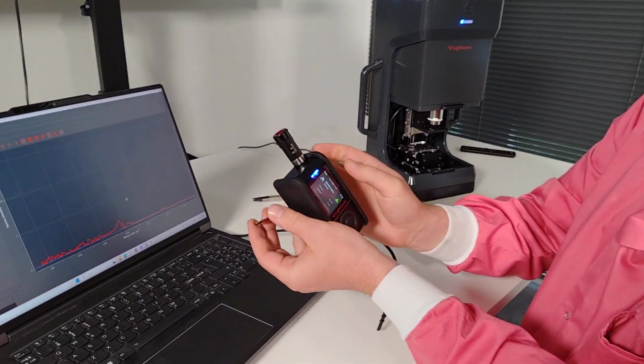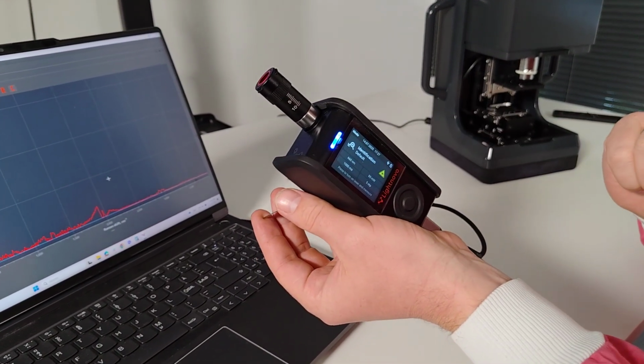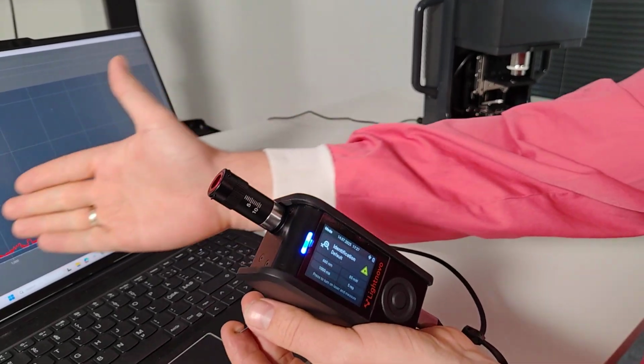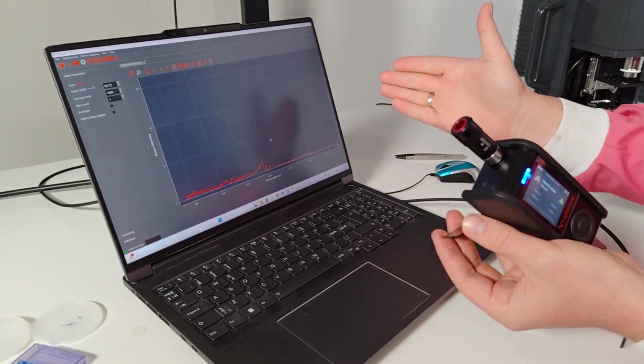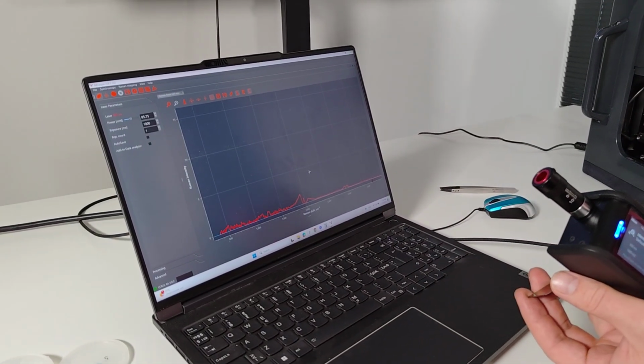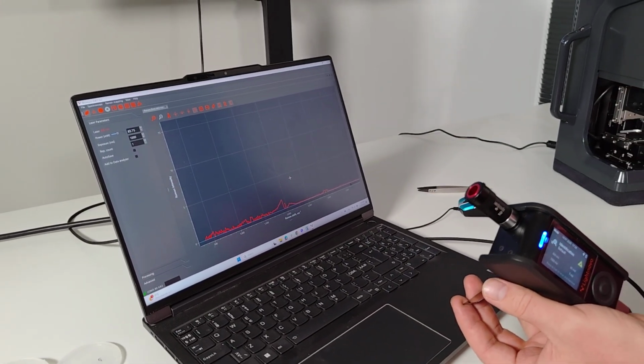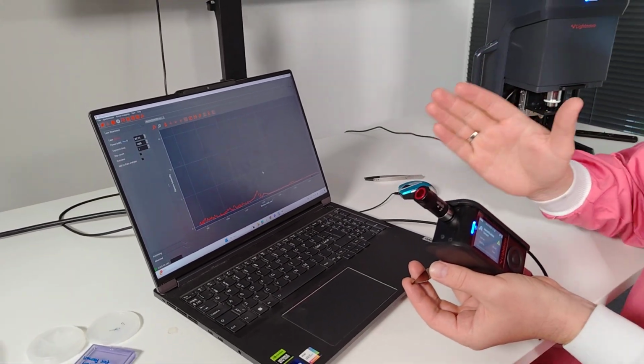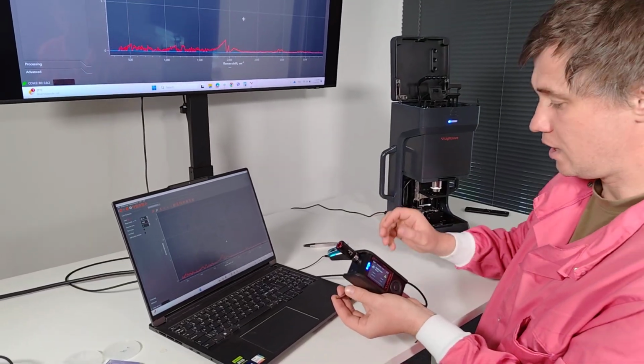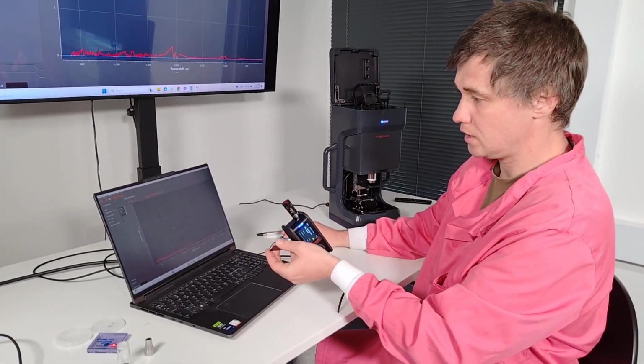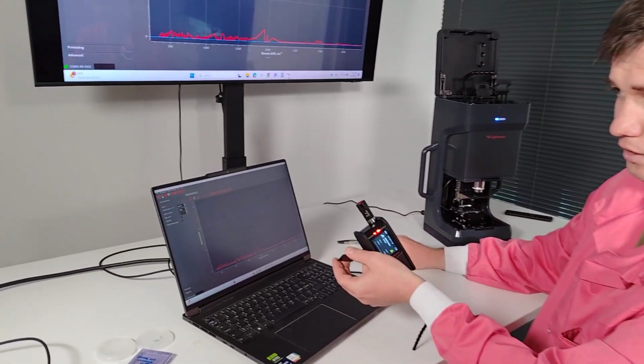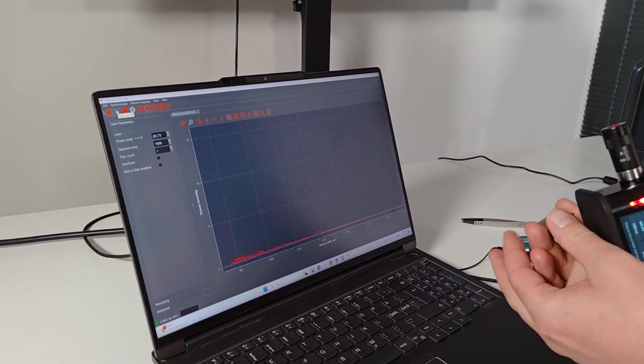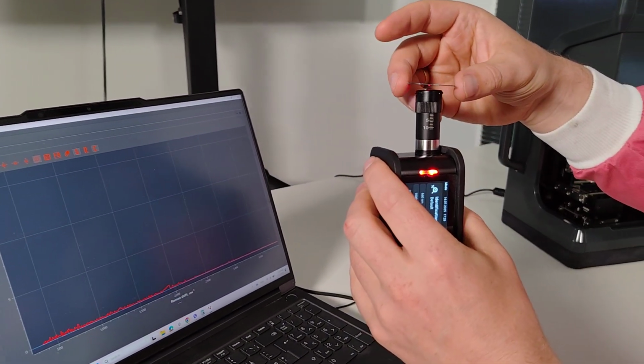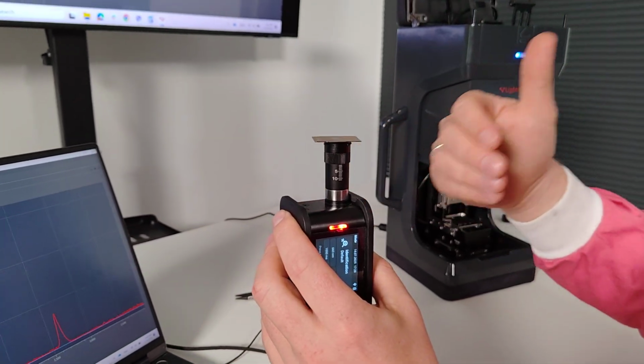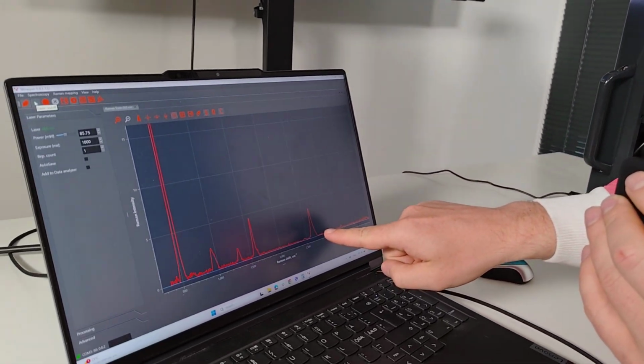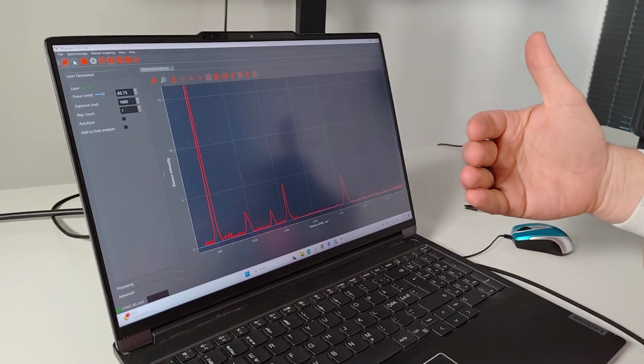Now our spectrometer has inside a 660 nanometers laser, and it can operate in the range from 300 inverse centimeters up to 4000 inverse centimeters with average resolution across the spectrum between 7 to 8 inverse centimeters. And this way, I'm turning on the laser light and I'm placing a graphene sample on top of the probe. And you can see immediately how the spectra of graphene appear.